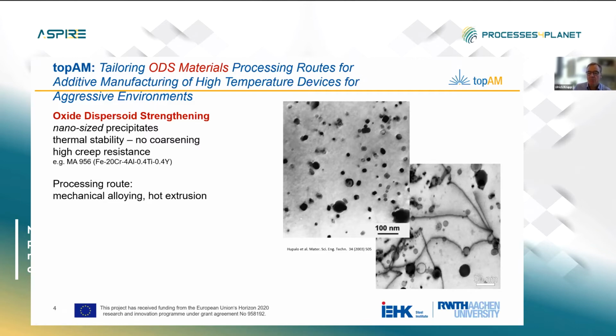And that is only possible either by strictly controlling the chemical composition or by mixing hard oxides into the alloy powder. Here you see an example of a mechanically alloyed material. Mechanical alloying in combination with hot extrusion is today the method to produce bulk ODS materials.